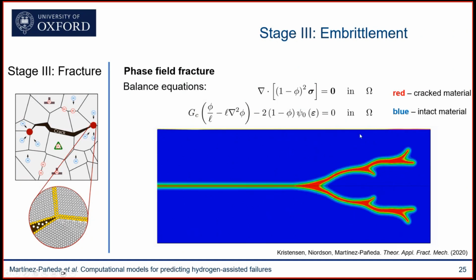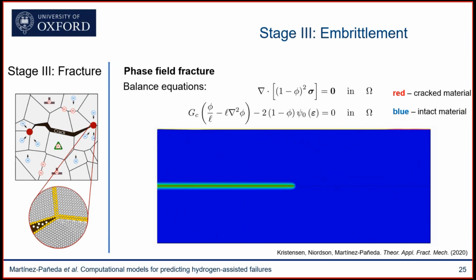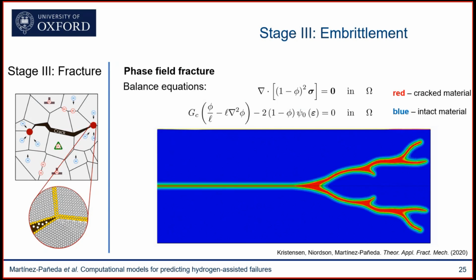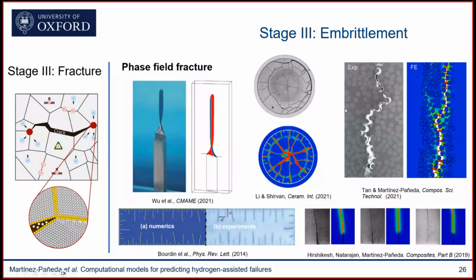You can see here in this image how you have crack branching due to the application of a dynamic load. And we can predict this complicated fracture phenomena without any convergence problems. The method is computationally very robust and the original finite element mesh. And I mean, this slide summarizes why it has been so popular in the computational fracture mechanics community. You can see here that it not only is able to capture very complex cracking phenomena, but is able to do so providing a remarkable agreement with experiments.